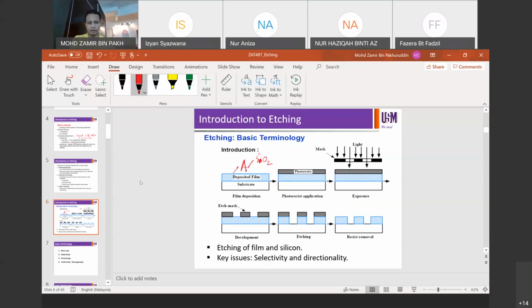If you have grown oxide, silicon oxide on top, you've grown on the whole surfaces of silicon, but you remove the oxide at the sides and at the back, so you're now left with the top oxide. Then you spin the resist, you send the wafer to bake process, you spin the resist, and then you expose some areas and leave other areas unexposed, just like what we learned in the lithography process. And then you develop the patterns, so you are now ready for your etching process.